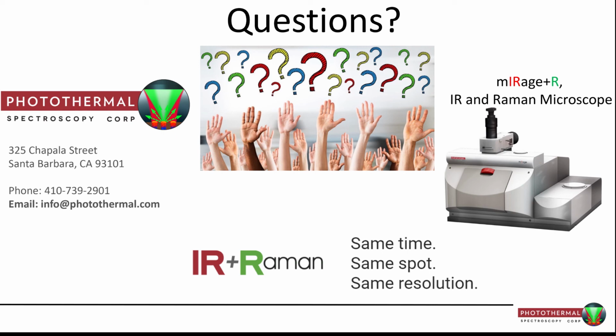And for people who are really keen on minimizing the fluorescence on the Raman as well, we do also offer a 785 probe beam in place of the 532. So of course, being a slightly longer wavelength, you're less susceptible to fluorescence. And the usual trade-offs in Raman are still there when it comes to 785 versus 532, when it comes to, say, sensitivity,